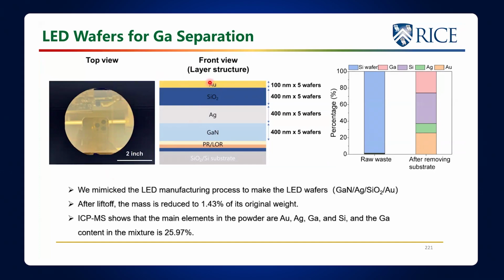So the wafer has gold, the wafer has silicon oxide, silver, and the gallium nitride. And then there's a photoresist, and then the silicon substrate. Most of the weight is in the silicon wafer. There's a little bit in the metals that are there. So after you remove this from the silicon wafer, so now you're pulling these metals off the top, you can see the gallium, the silicon, silver, and gold.